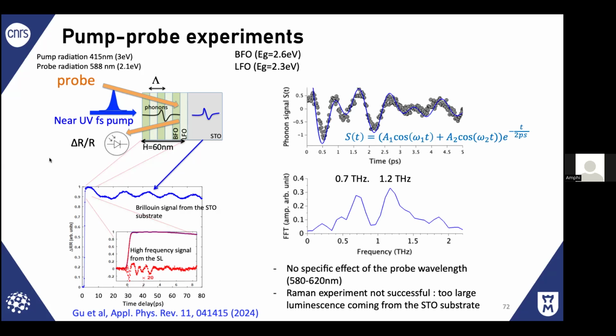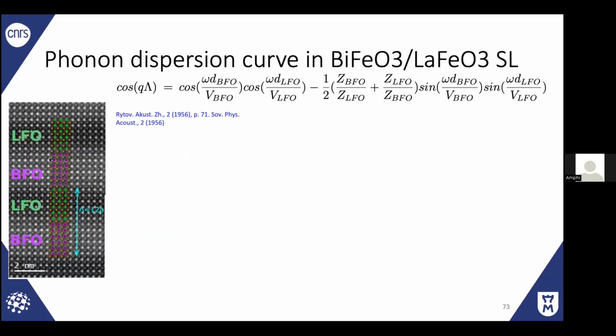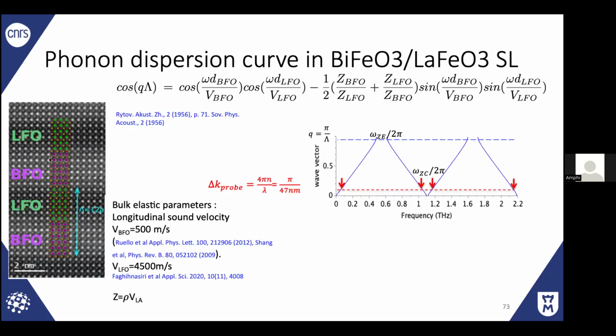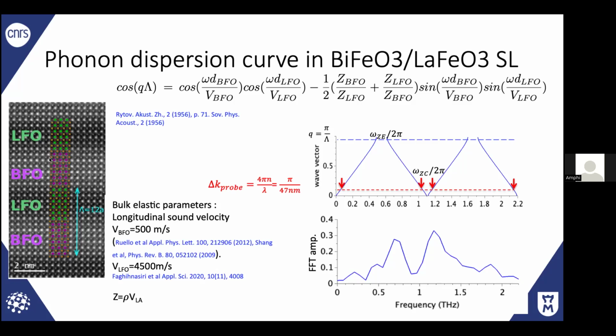What I forgot to tell you is that, of course, if you play with the thickness of the superlayer, I mean what we call the gamma, of course, you can tune the frequency. This is also interesting in superlattices. And so we did a phonon spectrum calculation, and in the phonon, we detect, sorry, that does not appear well. That one is what we expect. It works quite well. We expect that one that comes from just the mode folding. But that one, we did not understand where it comes from.